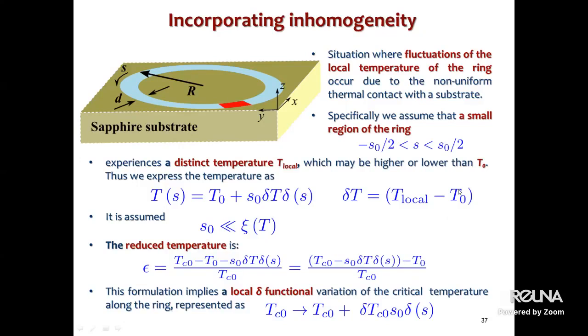The region with modified temperature is assumed to be much smaller than the superconducting coherence length. In this situation, the setup can be equivalently described as a localized delta function variation of the critical temperature. So our results apply to the system with uniform temperature but featuring a local variation of critical temperature, or, opposite to that, uniform critical temperature and local variation of ring temperature.